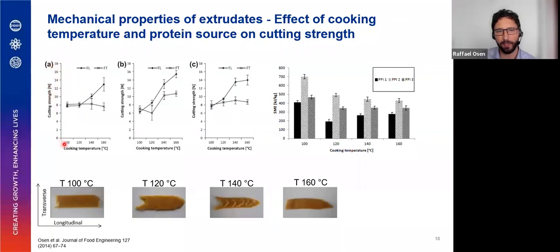Now, looking at the texture properties, this can also be seen in the graphs here, showing the cutting strength and the cooking temperature, that with increasing cooking temperature, the lengthwise fiber strength increases. We do see a small, let's say, difference in protein ingredient number 2. And this is shown here at the temperature below 130 degrees C, with some variation in the texture strength.